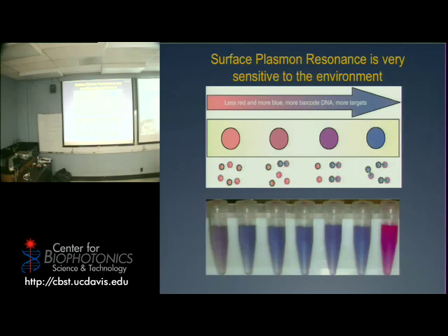And sometimes even just a speck of dust, something that has a little charge, can act as a nucleation event and trigger an aggregation event, and as we studied before, once it starts, it's hard to stop. So they give you an expiration date that has no real meaning. If you keep them well, you can use them for years. If you don't keep them well, you probably can use them one day, and then you're done, essentially.